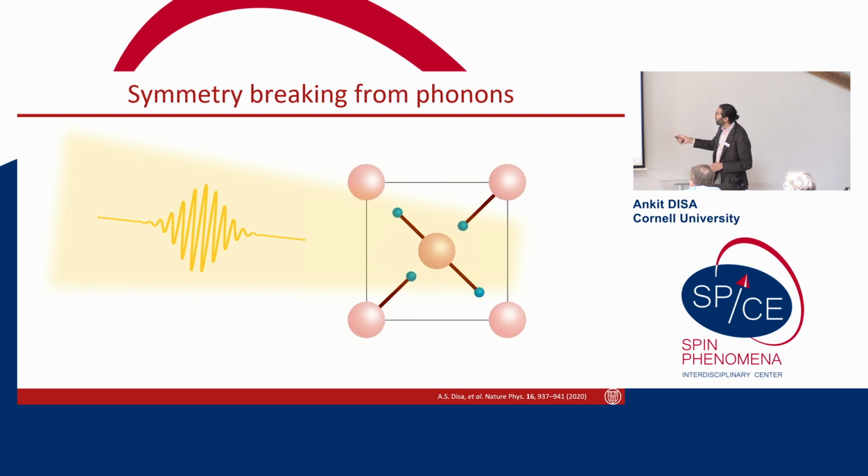And over time, what you see is that you end up actually stretching this bond length here, and on average, this bond length gets smaller. Okay, that's the coupling between the driven vibration and this Raman active mode, which we care about. So essentially that's what we're trying to do in the experiment.